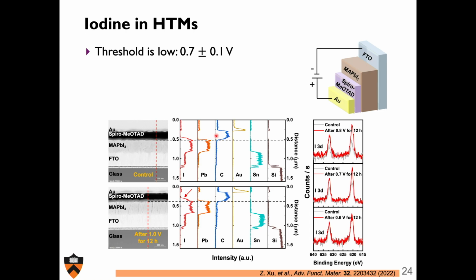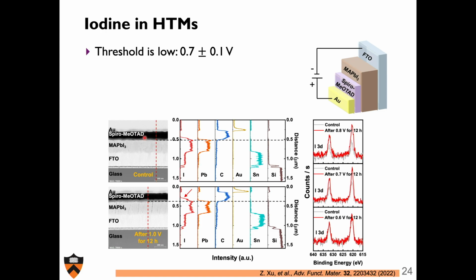You can see there's a pretty abrupt interface between those two profiles, between methylammonium lead iodide and spiro. Look at how much iodine has just soaked into this system. And that's just spontaneous. Upon spinning spiro on top of an iodide perovskite, substantial amounts of iodine leach in. And if I put a bias on this thing, go to 0.6 volts, not much happens. At 0.7 volts, look at my iodine signature, it's gone up. At 0.8 volts, it's gone up even more. And if I put this back in the TEM after 1 volt for 12 hours, you can see this zone of iodine infiltration has expanded.